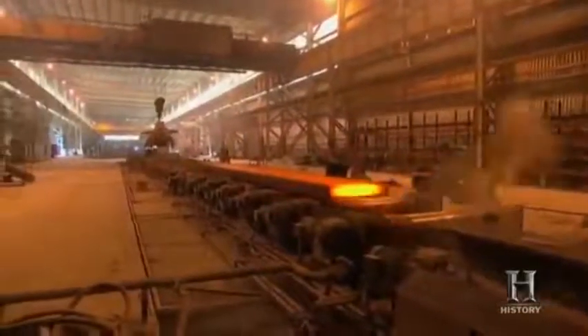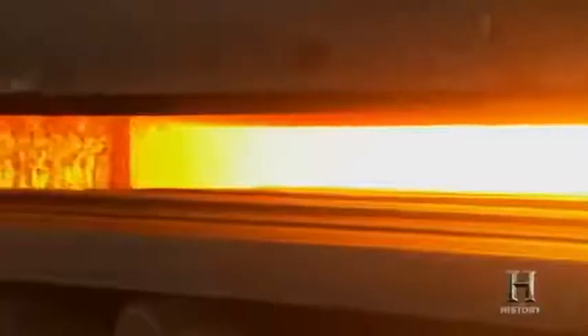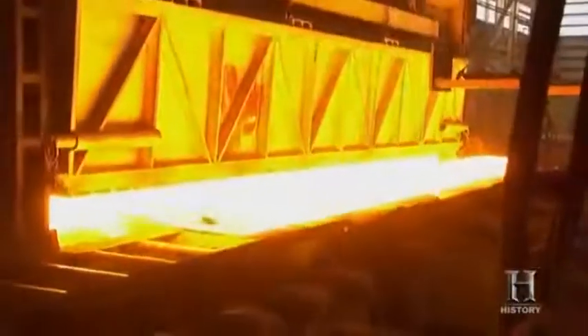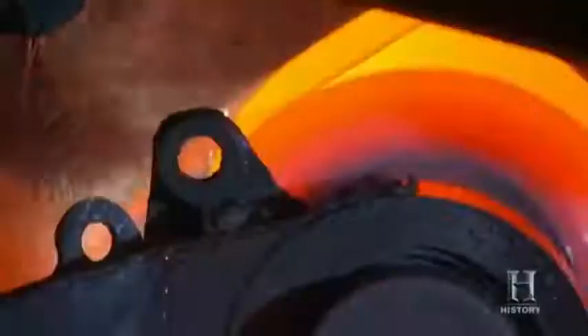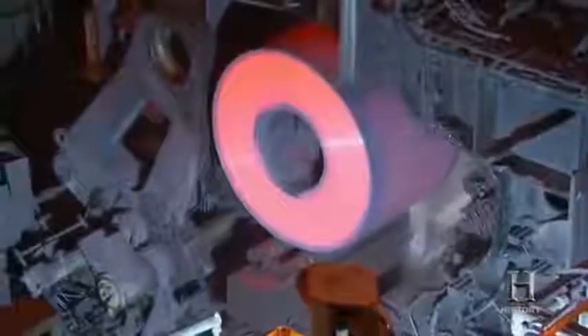They're brought to the hot mill furnace, which is behind me here. At that point in time, they are placed into the furnace, and they're in the furnace approximately 2.5 hours to reheat those slabs to around 2,320 degrees Fahrenheit to reduce their strength so we're able to hot roll the product. The hot mill uses 2 rollers to compress the 43-foot-long, 8-inch thick slab to a 2,000-foot-long coil, just under 1/5 of an inch thick.